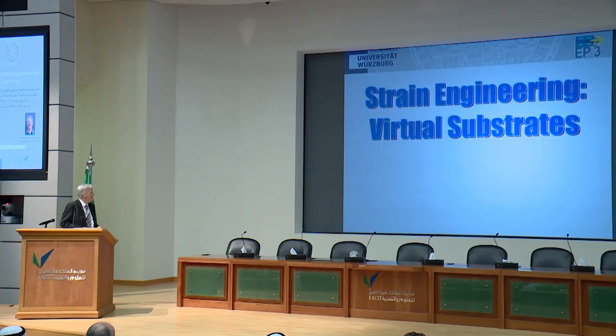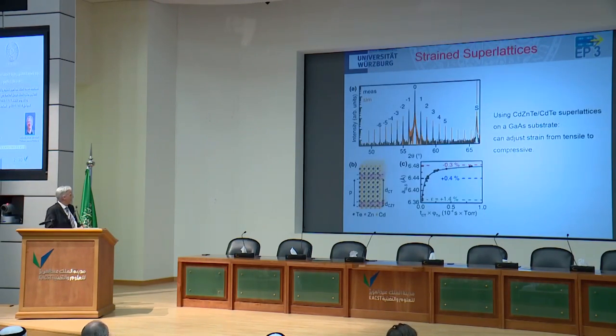Okay, the last few minutes of the talk is a bit more about strain engineering. This is work we've been doing recently. I already showed you that by growing on cadmium telluride, we can do tensile strain. Compressive strain would be nice, but it's way more difficult because there are no substrates available to do so. So what we do actually is we take a gallium arsenide substrate, which has a lattice constant that's way off. And now we grow a superlattice on this of cadmium zinc telluride, cadmium telluride. And this takes all kinds of tricks to do correctly.